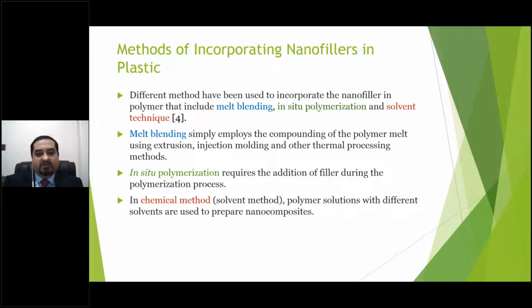Now, the various methods, most of you would know about them, that can be used for incorporating nanofillers in plastic include melt blending, in situ polymerization, and chemical methods. The most effective method in terms of production value is melt blending, because through melt blending we can use various techniques such as extrusion, injection molding, and other thermal processing methods to make sure that our nanofillers get incorporated within our polymers, and we get enhanced dispersion and distribution of the nanofiller along with the removal of agglomerates or aggregates or assembly of aggregates. If we are able to ensure that, then the polymer properties will be enhanced by the addition of nanofillers.